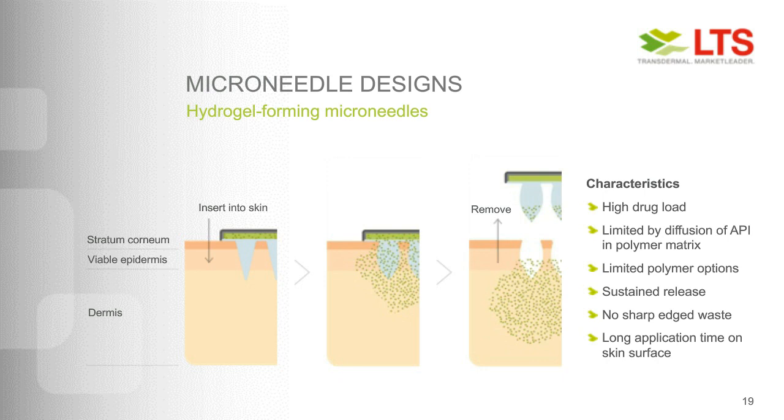Due to the water uptake in the skin, the polymer swells, takes up water, and it becomes from rigid to a more jelly consistency, and the API can move by passive diffusion through these polymer channels into the body. After the treatment, you just pull them out, and the hydrogel has such high cohesion that you just pull it out with the back plate.